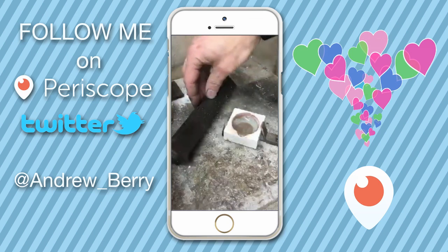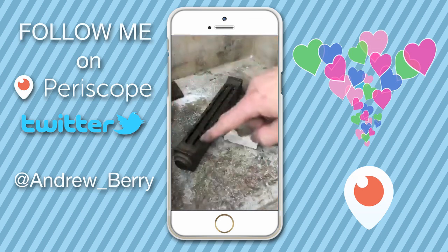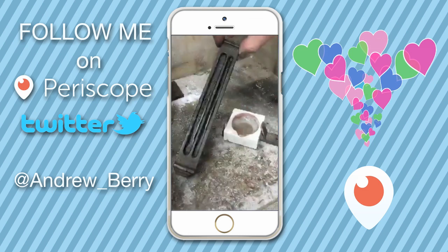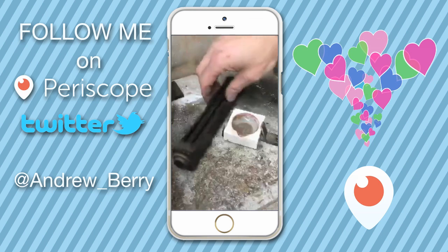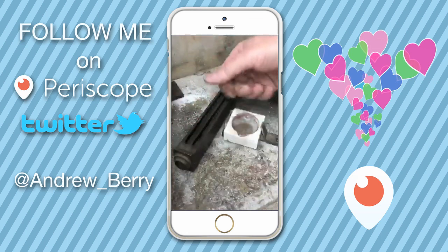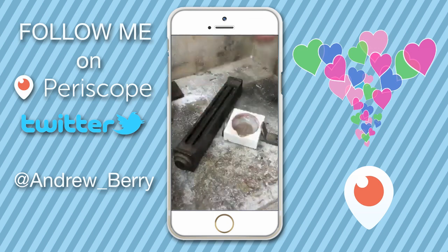As Shelley just said, she's having problems getting the paint off her ingot mould. Put some flame on it, put a lot of heat on it, make sure all that paint is burnt off, and you need to prepare the ingot mould by putting oil into this. It'll produce a carbon layer on the surface, which you can see my hands are getting filthy dirty just from touching, and then it enables you to get the silver or the gold out a lot easier.